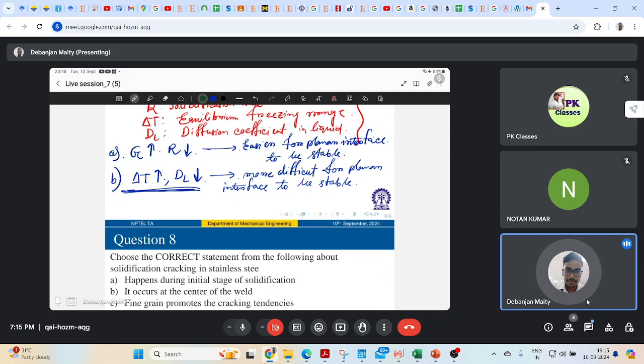So if you see solidification cracking now, where can you see solidification cracking? Wherever there will be this phase change, melting and solidification, right? So you can observe that in castings, in ingots, and also in fusion welding, of course. And these kinds of cracking are intergranular in nature. What is intergranular? The cracks will form along the grain boundaries of the weld metal during the terminal stage. I mean, it will not form at the initial stage of solidification. That will form in the final stage of solidification